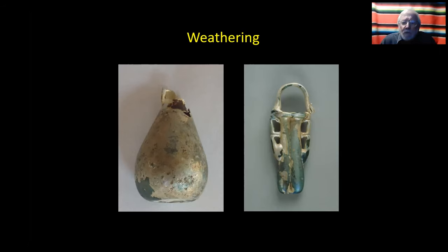The leaching of the alkali results in what we call weathering. We don't call it corrosion because it's very different from what happens with metals. The alkali is leached out, leaving behind a very thin layer of silica. And this recurs year after year or decade after decade. It's not entirely clear what the rate reaction is, but it's not like tree rings. This was tested out by Dr. Brill. He looked at glass from a certain period of time and put the glass under the microscope and tried to count the layers, and it just did not add up. So something stops it, whether it's temperature, whether it's more water, less water, we're not exactly clear on that one.